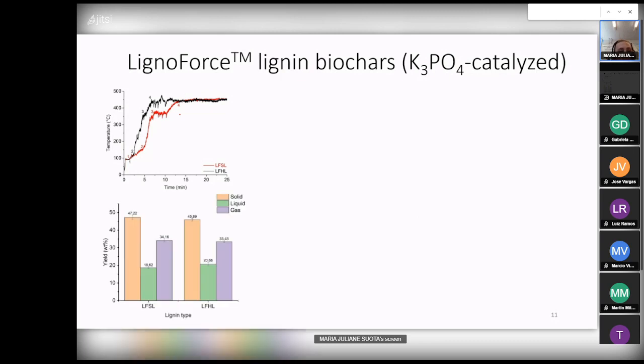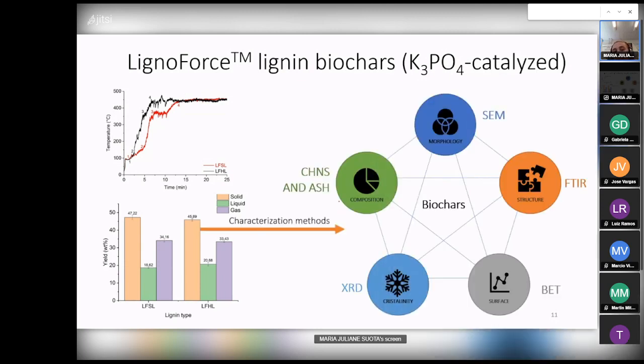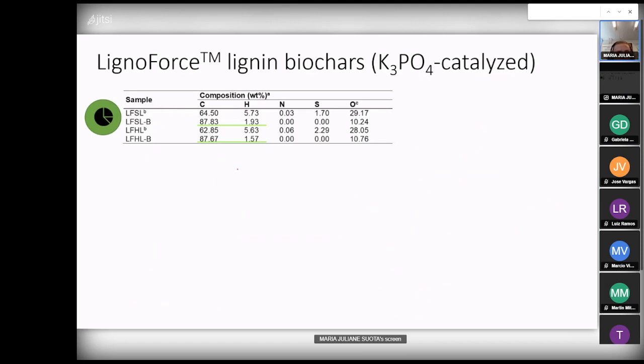This process generated solid, liquid, and gas, or biochar, bio-oil, and pyrolysis gas, and the biochar was the main product of this pyrolysis reaction. After this step, we decided to characterize this biochar, performing scanning electron microscopy, FTIR, BET for analysis of the surface area, and X-ray diffraction for monitoring the crystallinity, and also the elemental composition and ash composition. Those results were super promising.